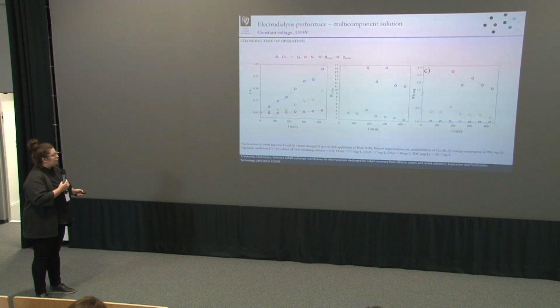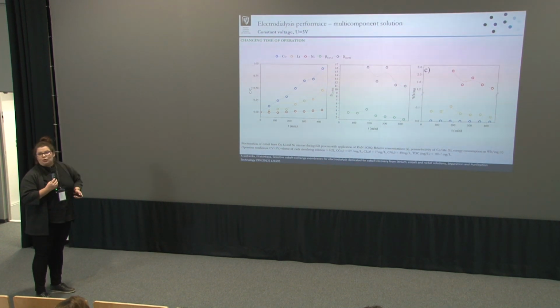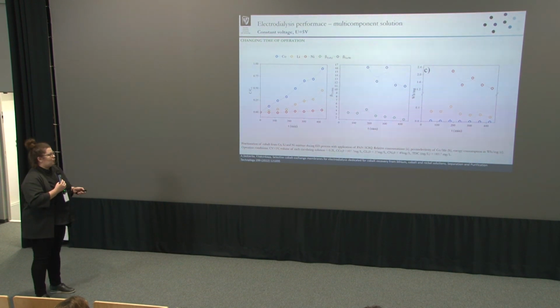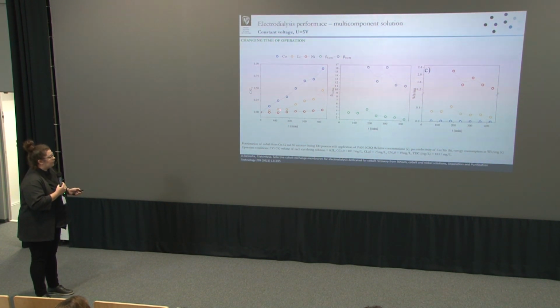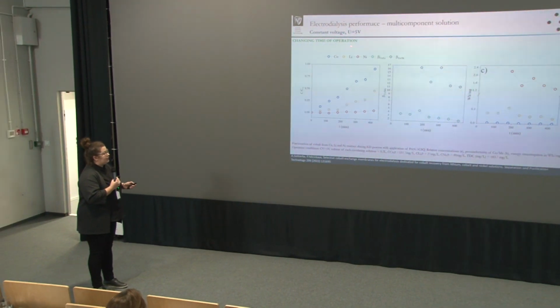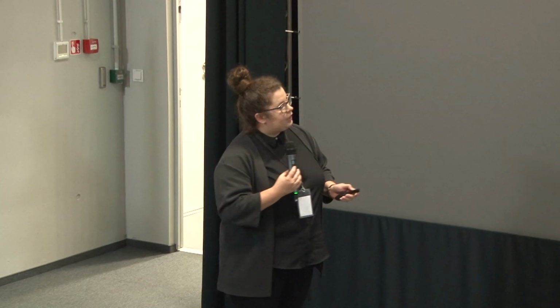So over time, we can find the cut-off time, the point where the selectivity, the selective factor between cobalt and lithium, just drops down. This is about 200 minutes. Here we can find the stable transportation of cobalt from the feed to the permeate.